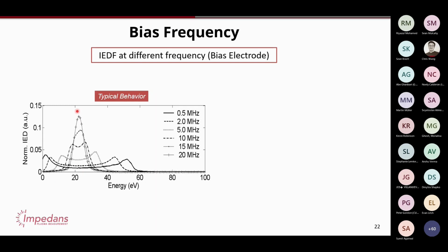And then as you go to lower frequencies, the ions can react more and more to this RF movement. So it sees the sheath oscillating, it sees the electrode voltage oscillating. So you start getting that bimodal splitting I mentioned earlier. And as you go to lower and lower frequencies, like this goes down to 500 kilohertz, you can get really wide peak splitting. This is advantageous, especially for etching. When you want to etch through the dielectric material, you need really high energy ions, and you need to sputter them.